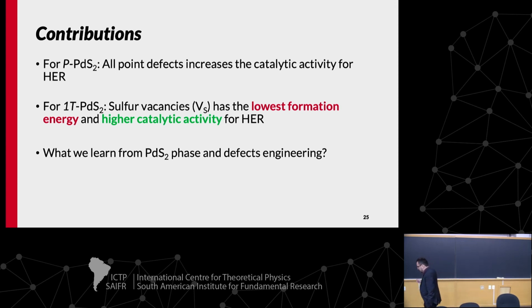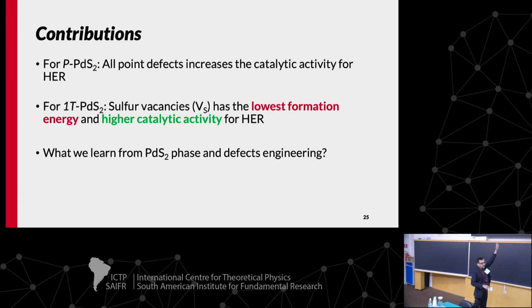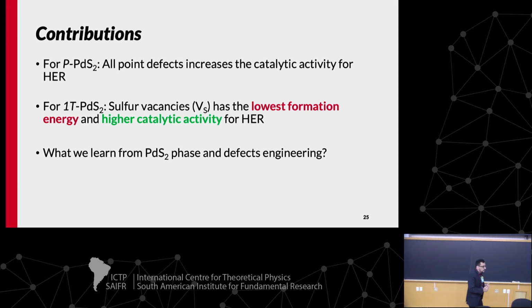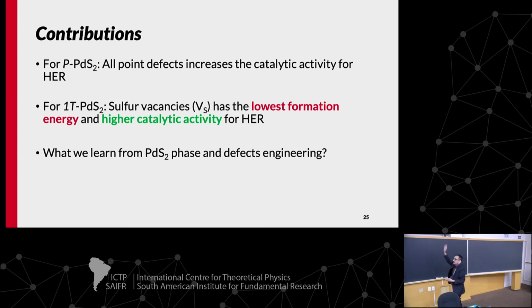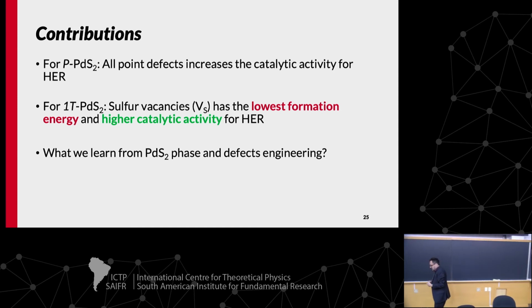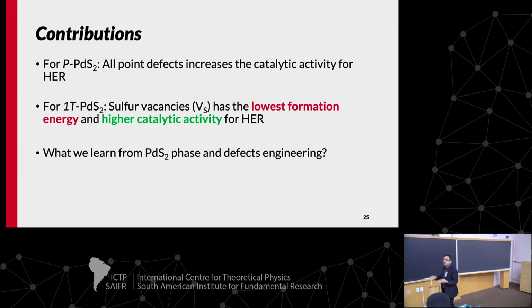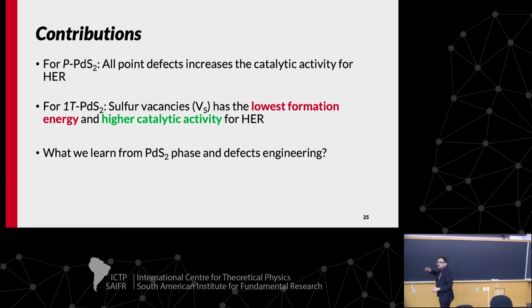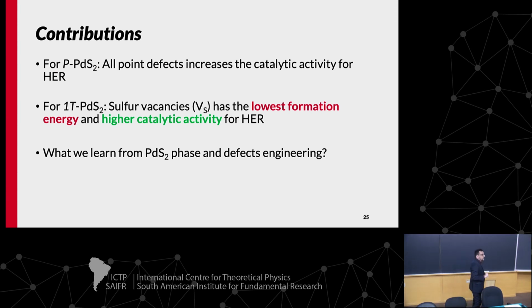But one thing I need to highlight here is what we can learn from this material, right? Even if we talk about not only one material, what we learned with MoS2, we can extend to PdS2, and we can extend to other semiconductors based on transition metal dichalcogenides or transition metal disulfides, right? We can see that they have some patterns, like sulfur vacancy can increase the catalytic activity. It's not a special case for molybdenum disulfide. Maybe we can extend it to more transition metal dichalcogenides, with different phases, different symmetries and different formation energies. We still have some similar patterns here. So this is what I'll talk about. So thank you.